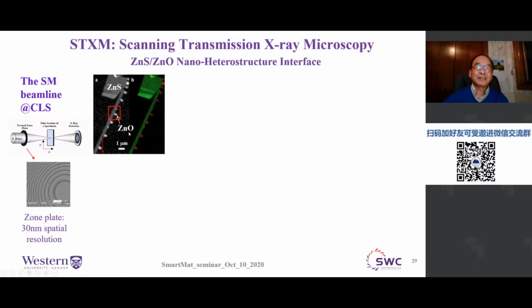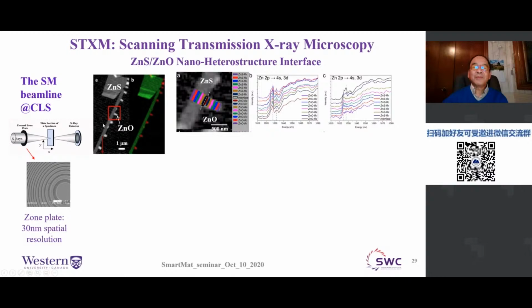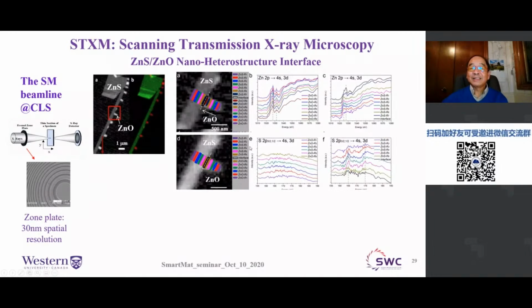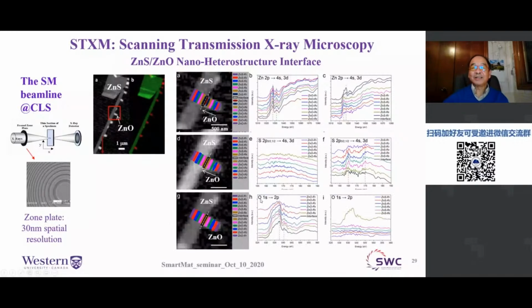We look at a zinc sulfide and zinc oxide heterostructure, right? So you pick this region, and we can do microspectroscopy or spectral microscopy along this junction. Let's say going from here, we can look at the zinc L edge excitation, and we can also look at the sulfur excitation, and the oxygen excitation. Obviously, when we are on zinc oxide, we only have oxygen, and when we are on zinc sulfide, we only have sulfur. Of course, you have zinc in both cases.